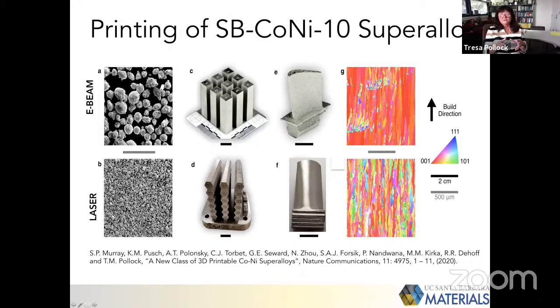One of the reasons for assembling all of these tools to try to do calculations on alloy compositions before we make powder is one of the major challenges of designing alloys for additive, because one must acquire powder. That means that you have a very expensive step in your design process, which involves atomization of the powder. And so one needs to assemble these tools to the degree possible and do those calculations prior to making the powders. So this is the alloy that I just showed you.